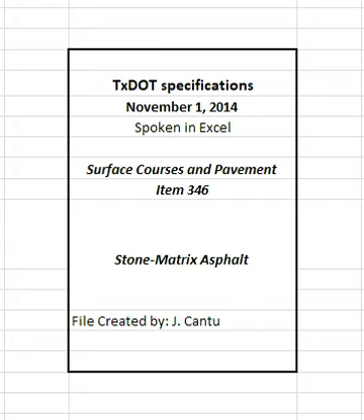4.7.3.4 Screed heaters. Turn off screed heaters to prevent overheating of the mat if the paver stops for more than 5 minutes. The engineer may evaluate the suspect area in accordance with section 346.4.9.3.3.4, recovered asphalt dynamic shear rheometer, DSR, if the screed heater remains on for more than 5 minutes while the paver is stopped.